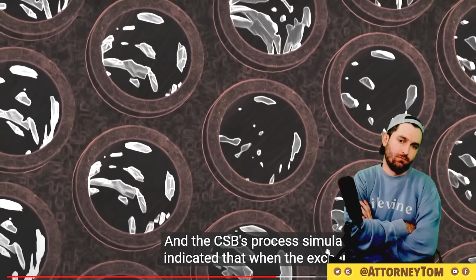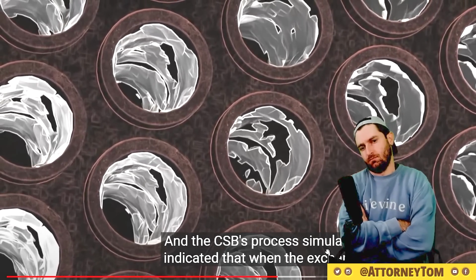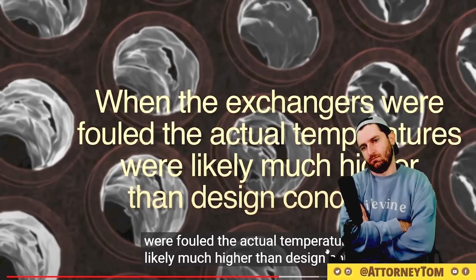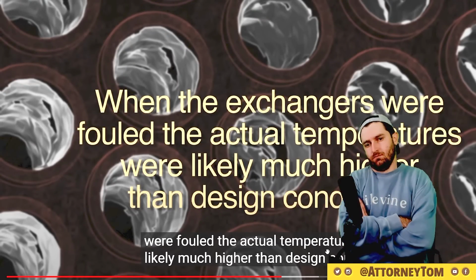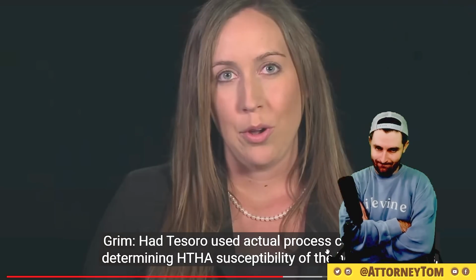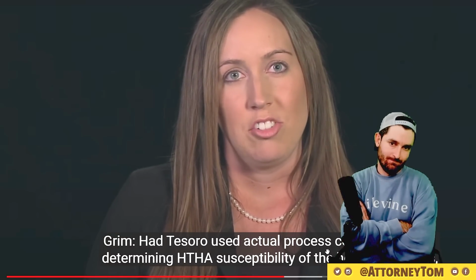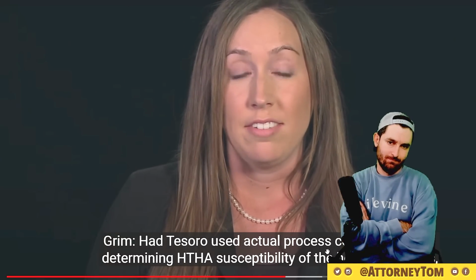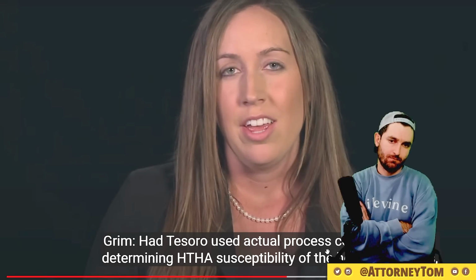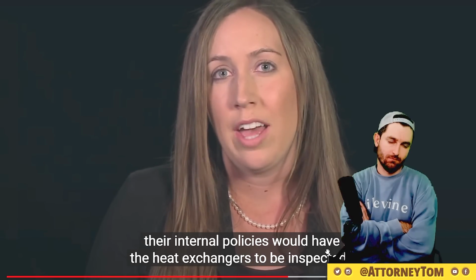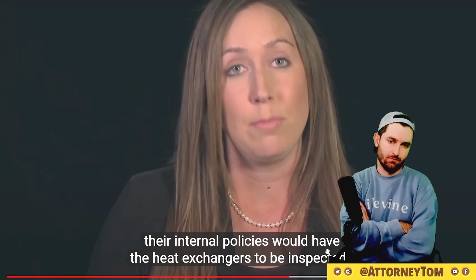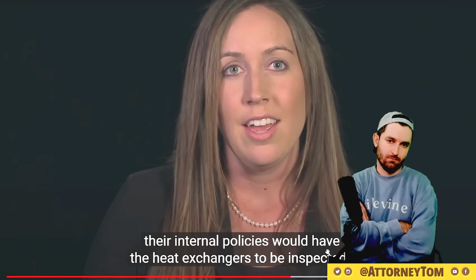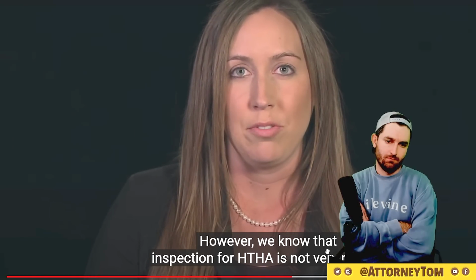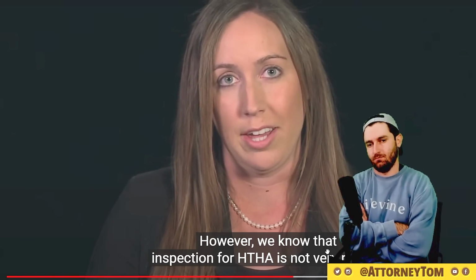And the CSB's process simulations indicated that when the exchangers were fouled, the actual temperatures were likely much higher than design conditions. Had Tesoro used actual process conditions when determining HTHA susceptibility of the heat exchangers, their internal policies would have required the heat exchangers to be inspected for HTHA. However, we know that inspection for HTHA is not very reliable.